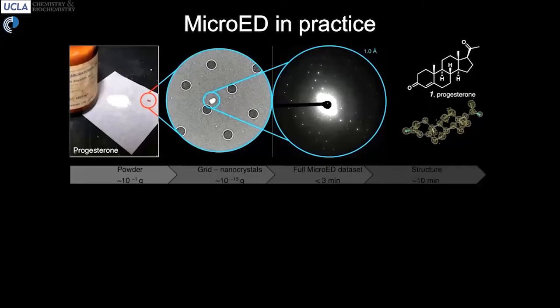Now, this can happen relatively quickly if your samples are ideal for this purpose. If you have a very small crystal of a sample, say a small molecule, it's very well ordered and diffracts very well. It's robust, doesn't get quickly destroyed by the electron beam, and it's happy to be dry in atmosphere. Then you can put it into the microscope, collect a diffraction movie or a diffraction pattern, and then try to generate a three-dimensional structure from it. And you can see in that three-dimensional structure, you can identify the position of atoms by looking at locations where you see spheres of density. So you see, okay, this is where an atom must be. Now, that's in an ideal case.